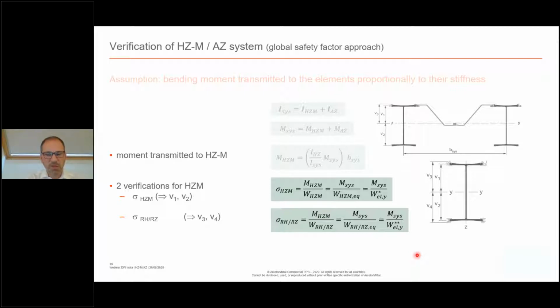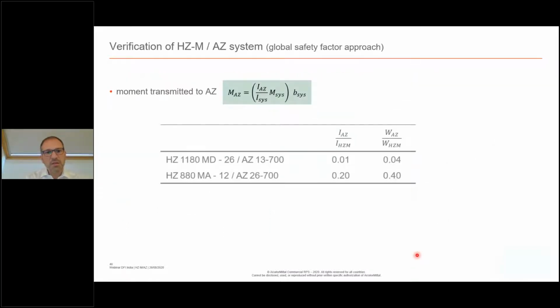So it's relatively simple. And in our brochure, you'll find what we call equivalent section modulus. So two values, one for the HZ and one for the connectors, because they don't necessarily have the same stresses, and they don't necessarily have the same yield strengths. And this is how you can calculate the stresses in those two elements. And for the infill sheets, it's the same. So you take the inertia of the infill sheet and you divide by the inertia of the system.